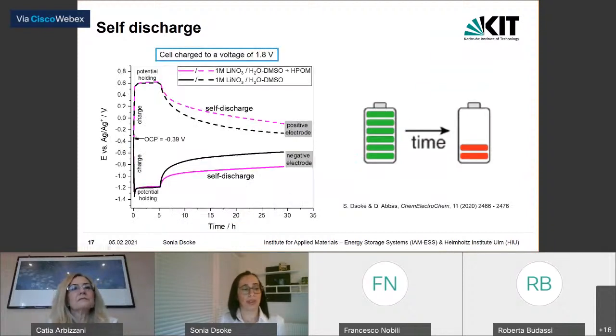What we did was to make this experiment. We charged our device up to 1.8 volt, and here you can observe the positive and negative electrode, which are monitored by a reference electrode, and we hold the potential for several hours, 5 hours in this case, and then we let the system relax and record the potential of the positive and negative electrode here. And you can see that there is a drastic decrease in the potential in both cases. However, there is a mitigation effect in the case that we have the polyoxometalate. This could be attributed to the fact that the polyoxometalate is able to strongly adsorb on the surface of electrodes. And this is something that was already proved before with other types of electrode substrates.